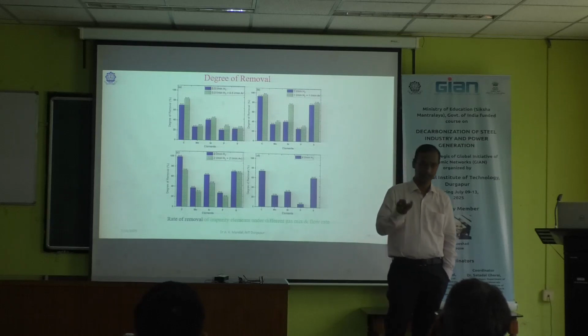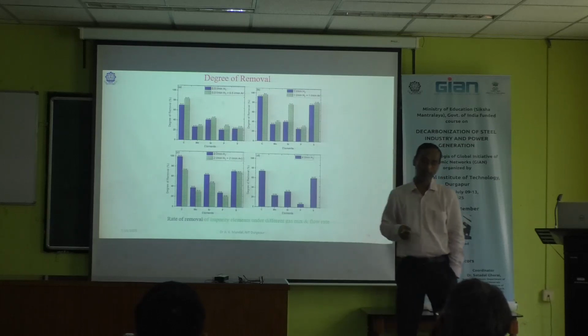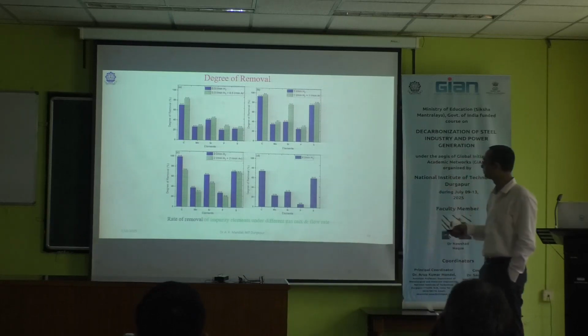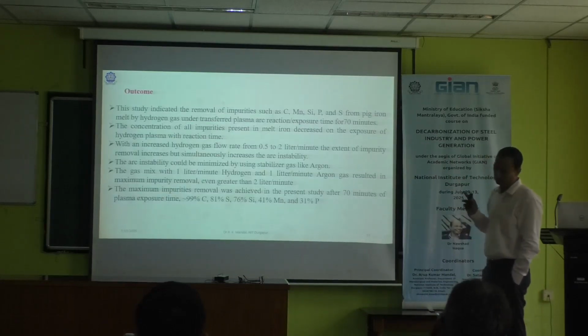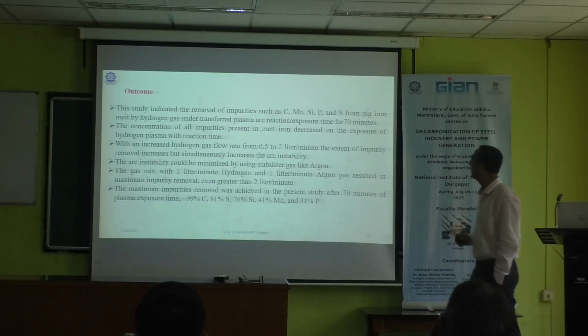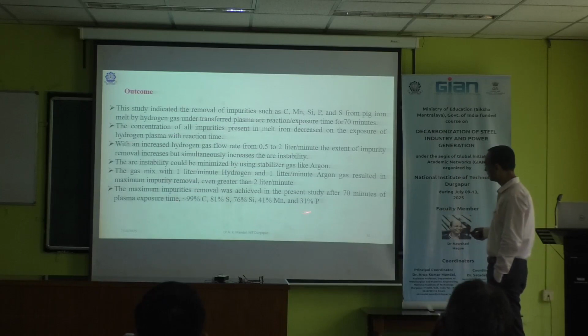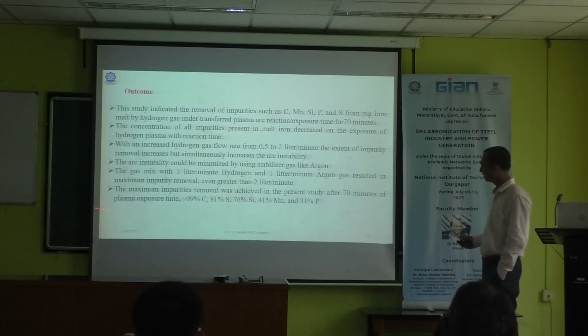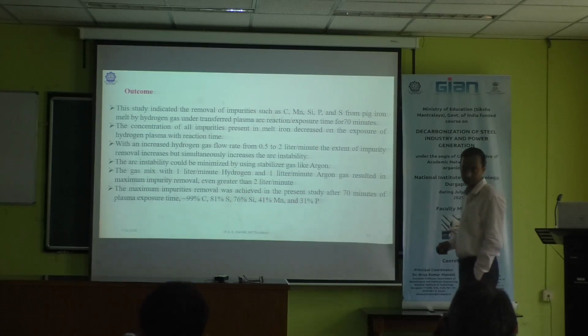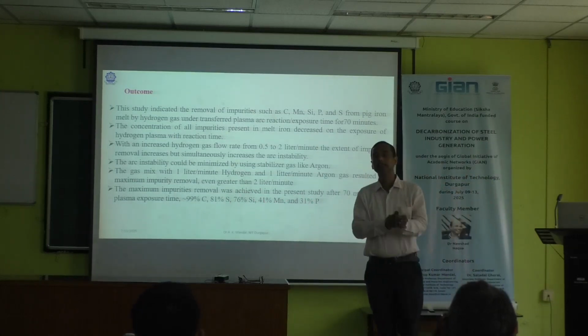And argon is the stabilizer gas. If you introduce some amount of argon, the stabilization will be more. So mainly from this study, we have got up to 70 minutes exposure time. We have got 99% removal of the carbon, 81% sulfur removal, 76% silicon, 41% manganese, 31% phosphorus. Then why manganese and phosphorus are less is one question in this.